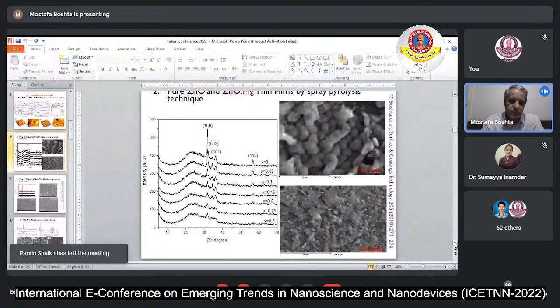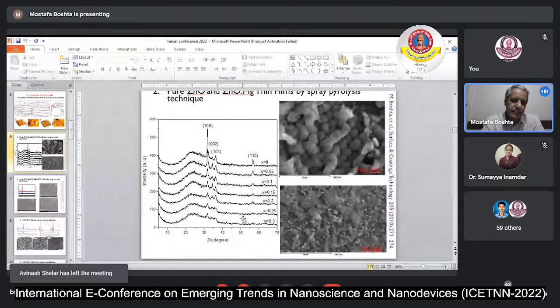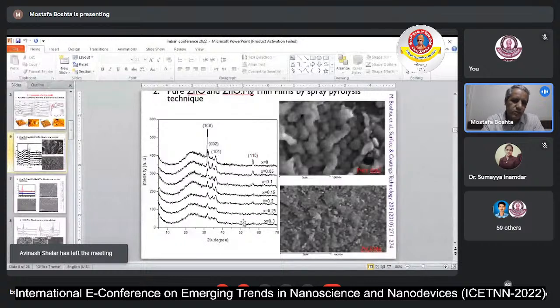As we see here, when we increase the magnesium additives to the zinc oxide, the crystallinity goes lower, and we lose the crystallinity of the material, but we didn't lose the small grain size of the surface, as we see in the scanning electron microscope. The grain size with the magnesium started to be small, which is the key to the efficiency of the photocatalyst application, which we will see the data for after that.